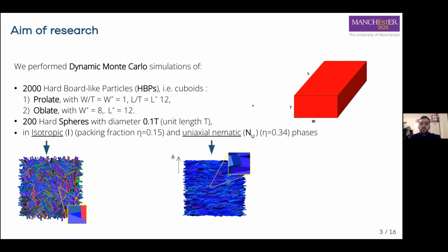And we perform simulations of cuboids and hard spheres that are much smaller than the extent of the cuboid, so they have a diameter equal to 1/10 of the thickness of the cuboid. And we investigated the dynamics of the mobile cuboids and the hard spheres in isotropic and uniaxial nematic phases.